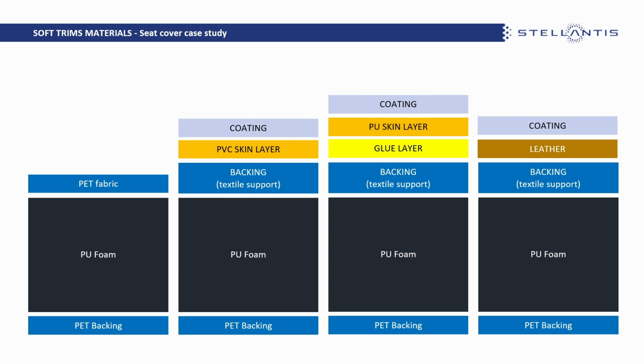In this case, we have 4 examples. The first one is related mainly to the fabrics structure. Then we have, again, the PVC structure for seat covers. Another structure using a polyurethane coating, a polyurethane skin, sorry, and the leather. In all the 4 cases, we have a polyurethane foam and a backing made of polyester. Also in this case, we can see that the structures are very heterogeneous. If I have to recycle this kind of material, it will be quite impossible. So the main way to reuse them will be to burn them to obtain energy.